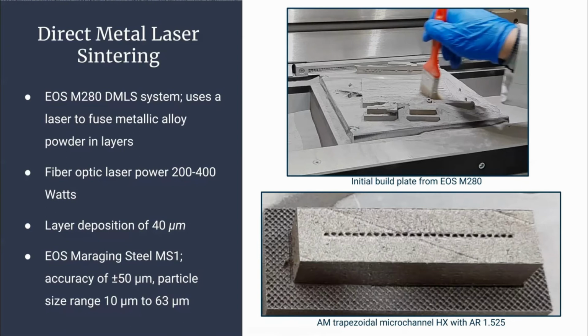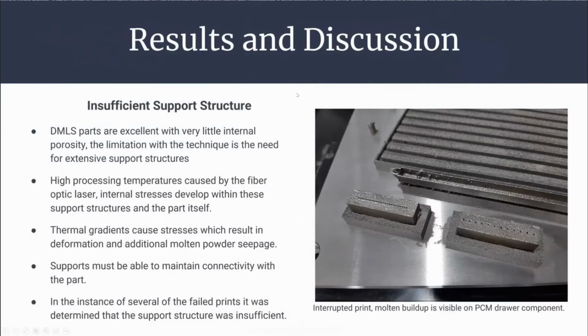We're using maraging steel in this, which is MS1, which has an accuracy of plus or minus 50 microns. So what we found initially printing is that we had some errors in printing. We had interrupted prints and aborted prints because we had an insufficient support structure. Essentially, we were trying to limit the amount of support structure that would have to be removed in post-processing. And what that was causing was, as thermal deformation hits the support structure, there's a lifting of the part from it. So this would interfere and come into contact with the recoater blade.